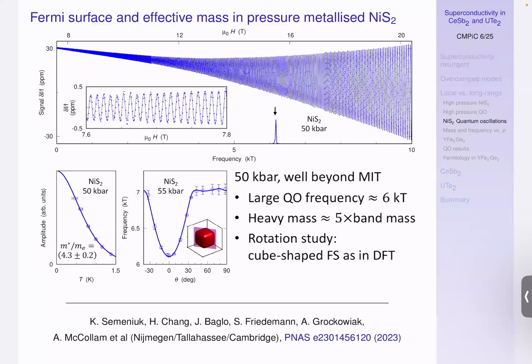It's ultra high resolution. So this was a measurement on nickel disulfide at 50 kilobar in a metallic state. And you see beautiful quantum oscillations at 20 Tesla, but going all the way down to less than 8 Tesla, clearly there at like 7.6 Tesla.